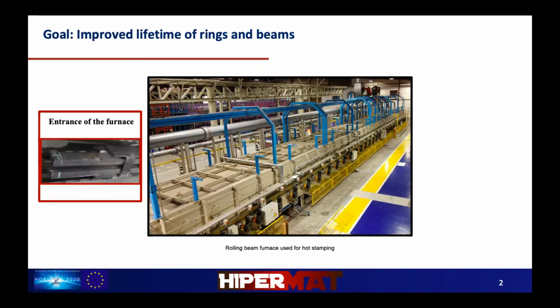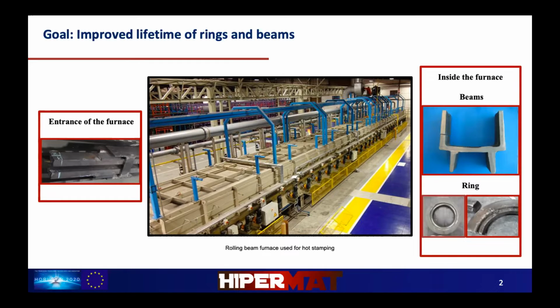There are two main paths focused in this project. First, the entrance of the furnace, where it undergoes fluctuating temperatures ranging from 450 degrees Celsius to 750 degrees Celsius and under high loads. And the second part of the project is focused on the inside of the furnace, which experiences a corrosive environment and continuous high temperature ranging from 930 to 970 degrees Celsius. These working conditions lead to failure modes of thermal fatigue, corrosion, creep, and wear, which were explained in detail by Fernando in the last presentation.